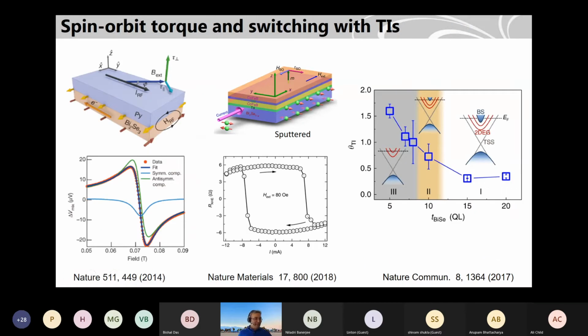Also, it's interesting to see how these topological insulators can be useful for spin orbit torque and switching with TIs. So there are lots of papers in the literature already. People have used bismuth selenide and BSTS, many kinds of compounds, with MBE, grown by sputter deposition, which gives not quite a TI, but just heavy elements, polycrystalline samples. So they also see very nice switching of the magnet.